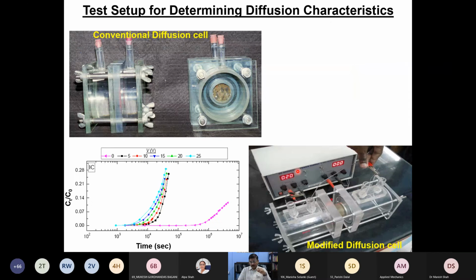you get the representative value. If you look at the basic equation, one is a sorption term, the second one is a diffusion term. In order to measure the diffusion, during my master's and PhD time, we fabricated this particular cell at IIT Bombay. Diffusion is also a very slow process. If you look at it, this CT by C naught is a very long-term process. For example, a diffusion cell has 3 components. One is a source reservoir, then the sample compartment, and a receiving reservoir.